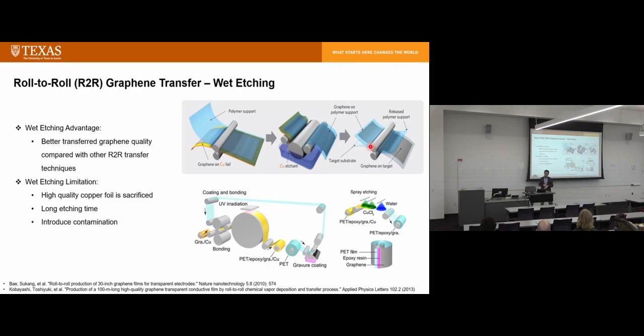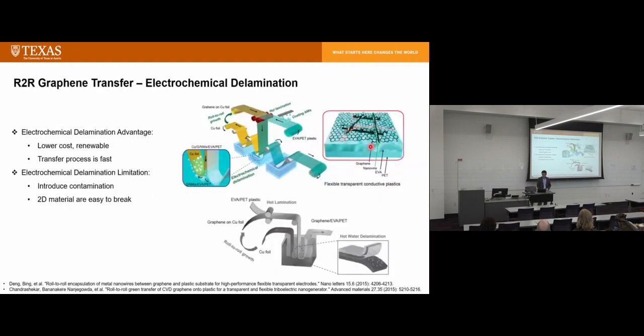So when you make graphene, you want this graphene to be pristine. There's no contamination, no charge attached to the graphene material. So later on, when you use graphene material, you can dope it, you can do other processes, you can make graphene useful. But for chemically dissolved copper, you do have pre-doped graphene, so the graphene property is already changed.